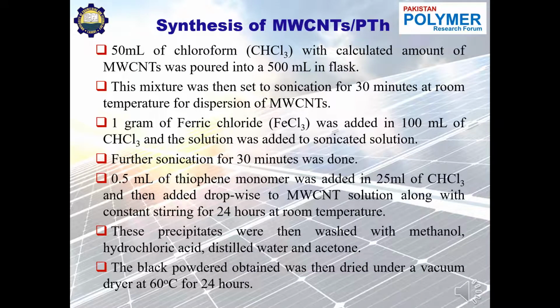After materials, I am going to explain the synthesis procedure of nanocomposite based on polythiophene and multi-wall carbon nanotubes. First of all, a calculated amount of multi-wall carbon nanotubes was poured in 50 ml chloroform in a round bottom flask, and the mixture was sonicated at room temperature for 30 minutes for the proper dispersion of MWCNTs. After the MWCNTs were dispersed, 1 gram ferric chloride solution was made with 100 ml of chloroform, and then this solution was added to the sonicated solution of MWCNTs. Further sonication was done for 30 minutes for the proper dispersion and oxidation of MWCNTs.